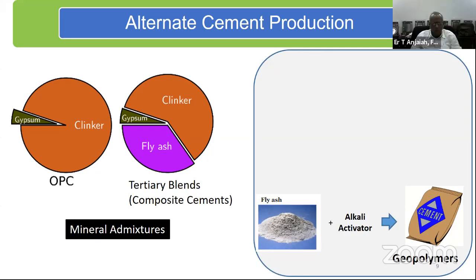We are able to produce cement such that we are reducing the clinker factor in cement. Through research, we have managed to reduce clinker factors in cement, sometimes down to almost 30% to 40% of the original clinker requirement of normal, ordinary Portland cement. So that is already happening. What that allows us to do is to stretch our resources significantly, reduce the environmental impact, and reduce the energy requirement in cement. So that is one way that we are trying to become more sustainable, where we are able to stretch the material to give us the required performance.